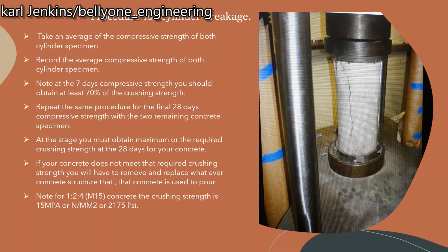Note that at the 7-day compressive strength, you should obtain at least 70% of the compressive strength. So you must have an idea of how much the ultimate compressive strength is going to be, the strength of your concrete. And when you do your first 7-day break, that equivalent must be at least 70%. So in the case of a 1-2-4 mix, the compressive strength is 2,175 pounds per square inch, or 15 megapascal. So when you do the initial breakage of the first two specimens, that's supposed to be equivalent to 70% of 15 megapascal, or 70% of 2,175 pounds per square inch.